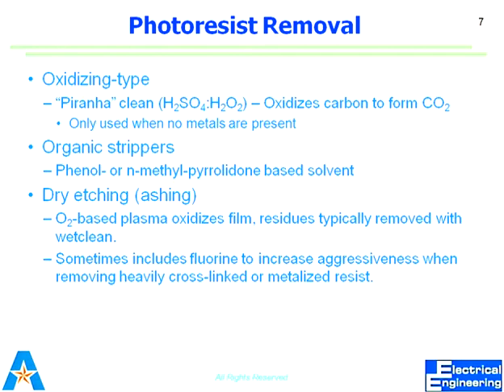In the lab, we use 3:1, if you remember, for this piranha clean, but some people use 7:3 as well, where H2SO4 is 7 and H2O2 is 3. So that's why I say different ratios are used for piranha clean, but even 1:1 is used. That's also good enough. Maybe you will have to heat it up. 3:1 is very hot by itself, and 1:1 would not be, but you will have to heat it up to 95 to 200 degrees centigrade before cleaning. It also takes time to cool down. Yes, it always takes time, approximately 45 minutes, depending upon the concentration you use and the volume. The volume that we used in the lab took approximately 45 minutes to cool down.